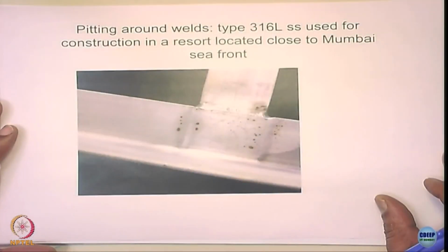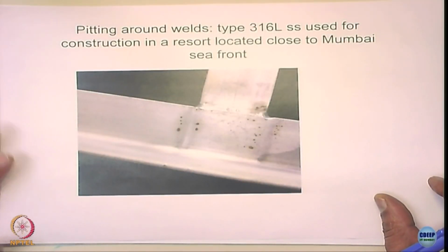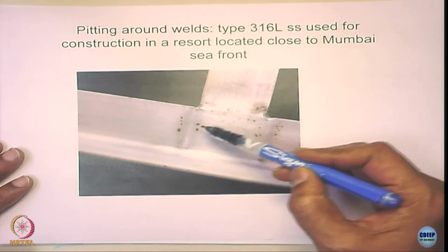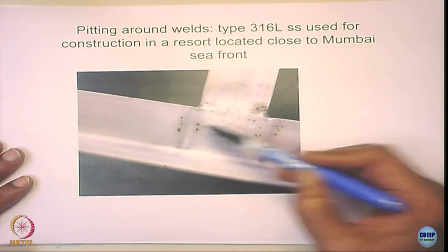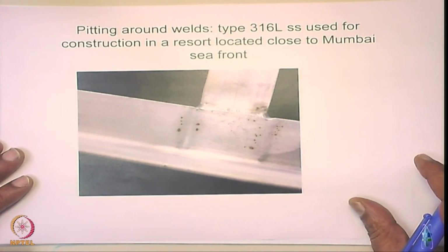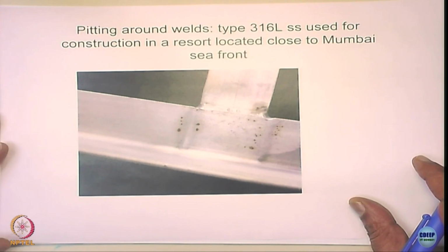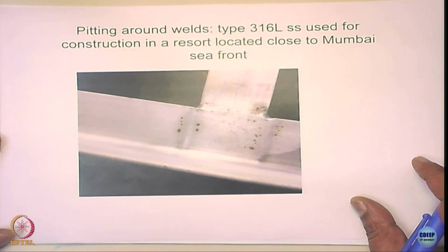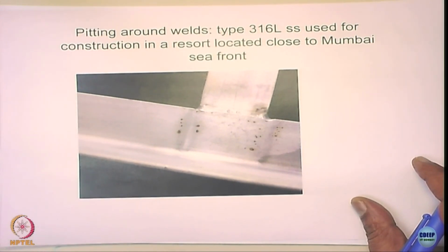They become very severe where they were welded. See that here, right? I hope you were able to see these reddish brown spots, okay. These spots do correspond to severe pitting. Two kinds of problems here. One is the loss in the structural integrity, otherwise the cosmetic appearance of the stainless steels, right.